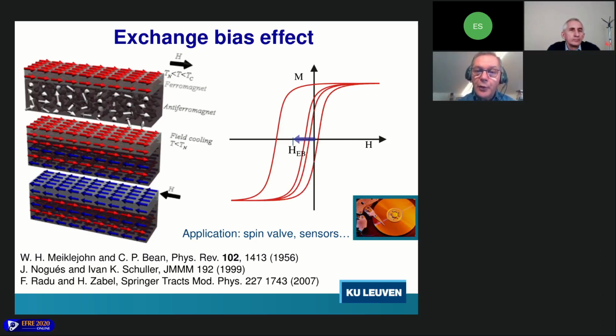And so this leads to a hysteresis loop that is much broader than that of the ferromagnet alone, and also the hysteresis loop is shifted along the field axis. The coupling is so strong that when you start diminishing the magnetic field, it really acts as a spring, and you will even jump back to the original magnetization direction even before you have reached zero field. And so this shift of the hysteresis loop, this is what we call the exchange bias.